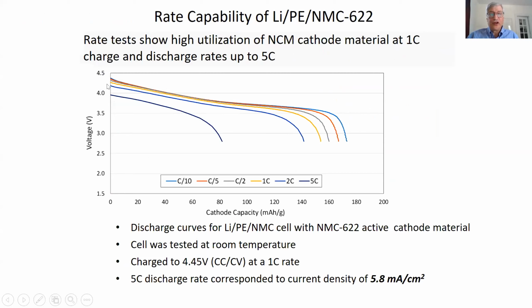And also, if you push it really hard, now if you want to charge your battery fast, or if you want to accelerate, you have to have a pretty high current density. And this is, again, a similar battery, lithium metal, not lithium ion, with a cathode made with nickel. It's a so-called nickel manganese cobalt cathode. And if you push it really hard, that's this curve down here, you can still get appreciable power out of it, we can sustain a current density of almost 6 milliamps per square centimeter. If you're a battery person, that means a lot because this is almost about a factor of 10 higher than has ever been demonstrated with any other solid electrolytes.